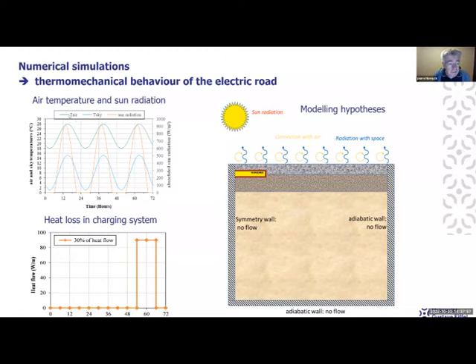We simulated air temperature variations, sky temperature variations, and also sun radiation. And then we proposed to simulate cycles of these temperatures to simulate daily variations of temperature. And then we added the heat loss due to the charging system. So from the laboratory test, we estimated the heat flow that would be generated when the system is in operation. And so the heat flow was about 80-90 watts per meter of length of the coils. And so we simulated this heat flow.